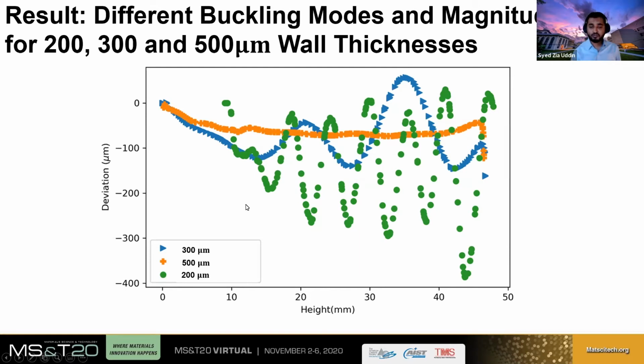As was pretty evident from our contour plots, we see a very high frequency buckling in the 200 micron wall thickness part, and then we see a lower frequency but still large out of plane deformation for the 300 micron wall thickness part. But as indicated in the contour plot, we don't see a lot of large deformation on the 500 micron wall thickness, although there is some. If we look at this gap from the 0 point to this point, we still see some overall shrinkage that was indicated by the overall bluish color. But in the 500 micron wall thickness, there is no big overall deformation and no big buckling type deformation present.